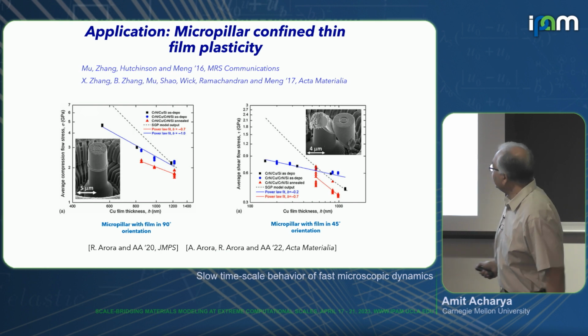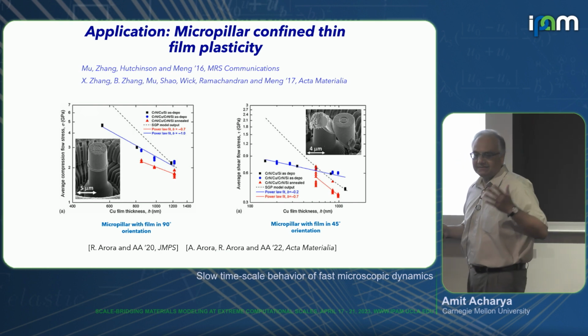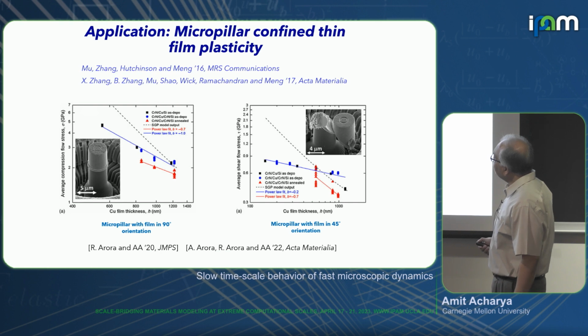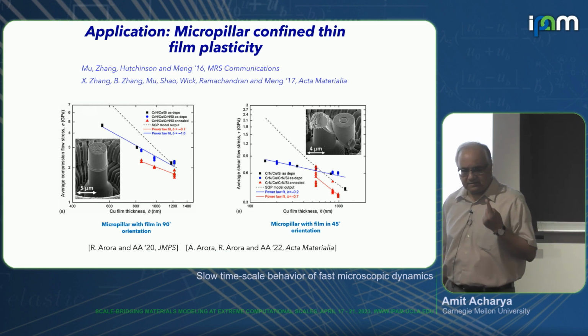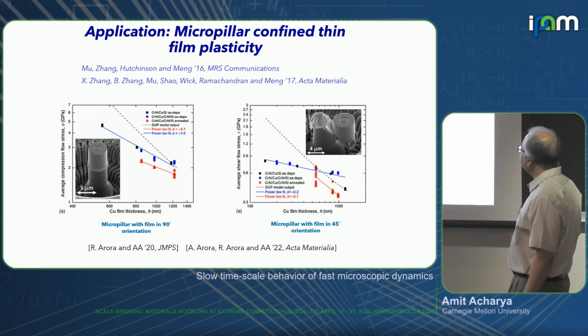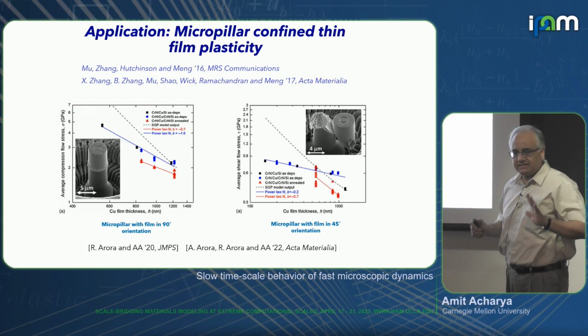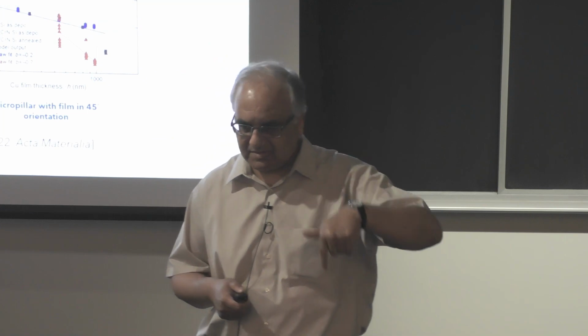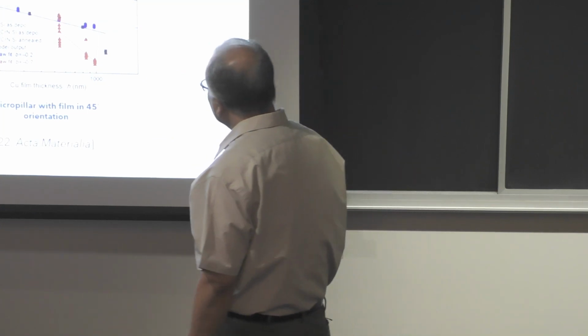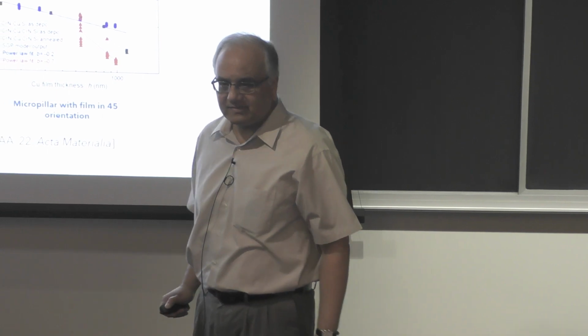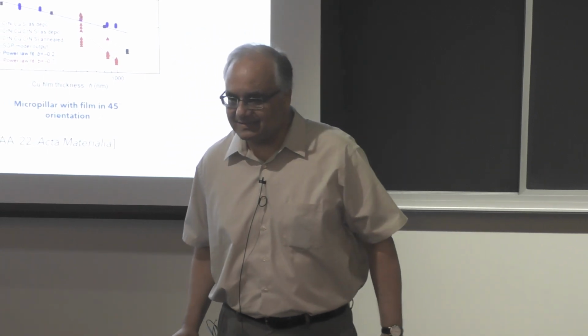So drastically, okay, the shearing off looks dramatic, but look at these results here. So the experiment for the as deposited film in the copper pillar, in this orientation, the log stress versus log of thickness, the scaling is -1, the exponent. In the 45-degree orientation, material remains the same, nothing changes. You're doing the same experiment, just the orientation change. There's almost no effect, okay? It's -0.2. Go figure, explain this.